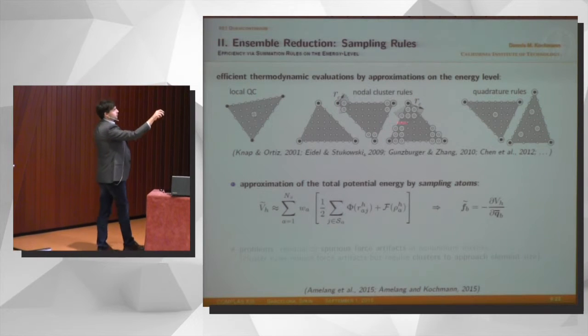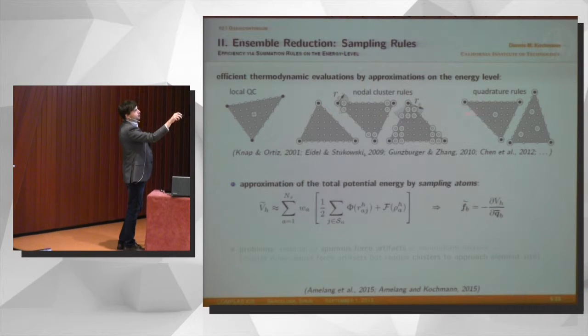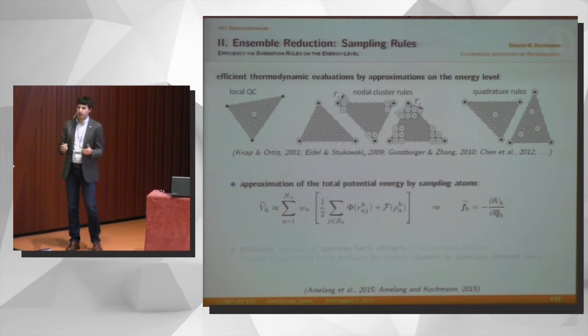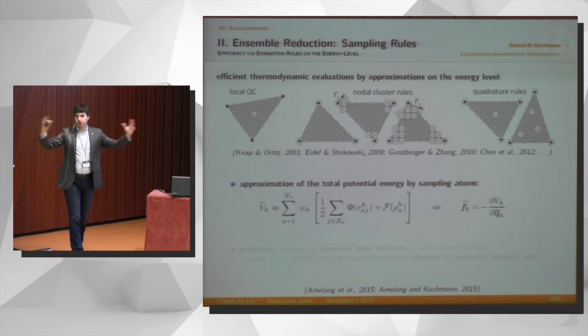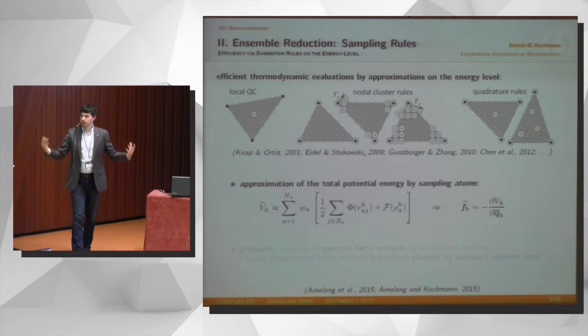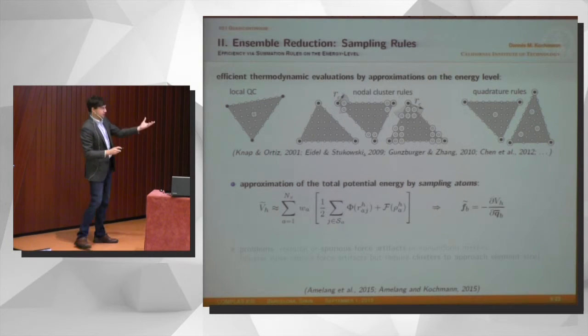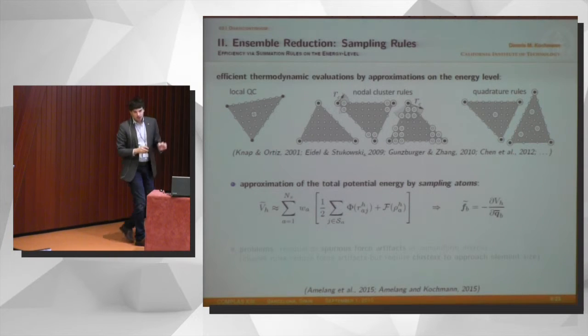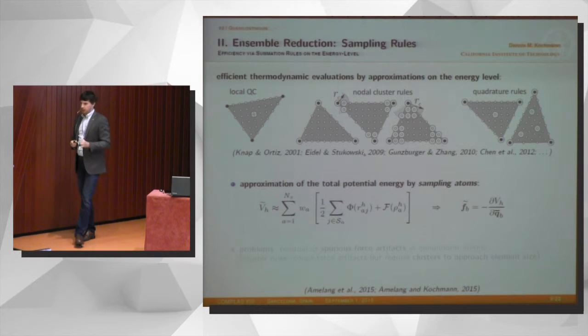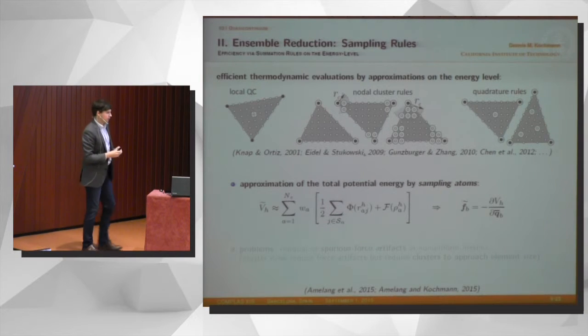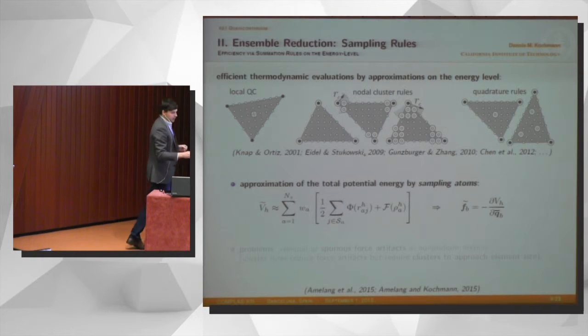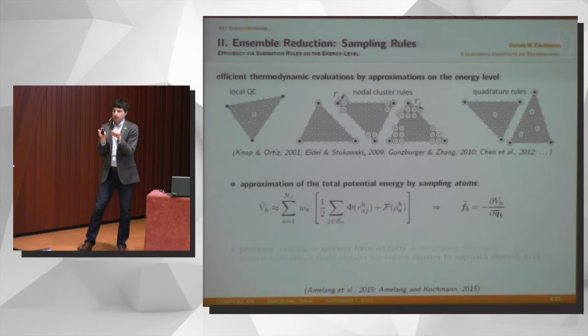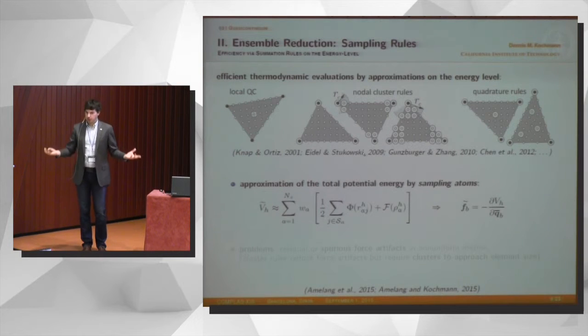What many people do is use clusters around nodes for higher accuracy, or you can do combined quadrature where you use the nodes and some points on the inside. But in any case, what we do is reduce the complexity by computing only the energy of a few representative sampling atoms. This, unfortunately, brings about a big issue that we, I think, have a way to solve now eventually, and that is when you approximate the energy by only computing the energy of a few atoms, you're making a mistake, of course. That's an approximation.